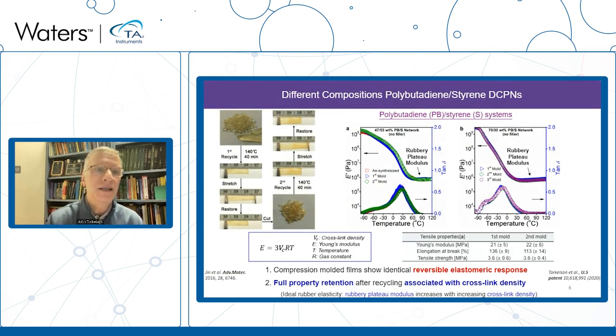So here we illustrate this case where we start off with the copolymer, we cut it into bits, and we can actually process this into films at 140 degrees C. You see elastic character associated with these films. We can take those films, cut them into bits again, reprocess them, and actually recover the elastic behavior associated with these. We can easily characterize cross-link density in these materials by measuring basically the tensile modulus or stiffness of these materials as a function of temperature.